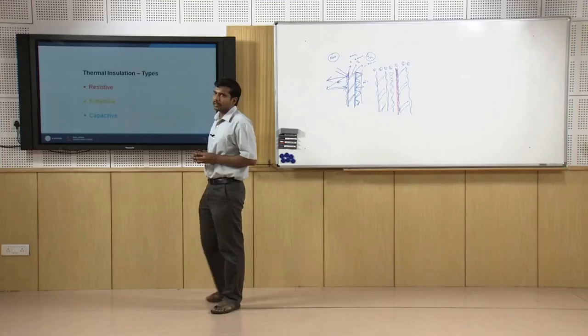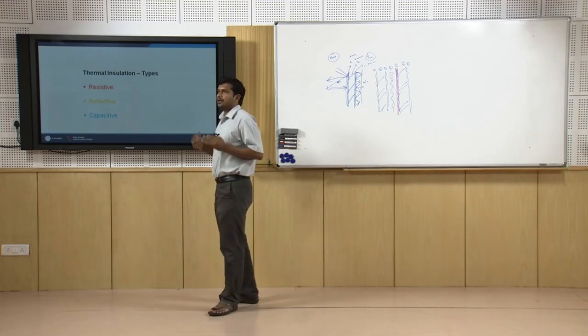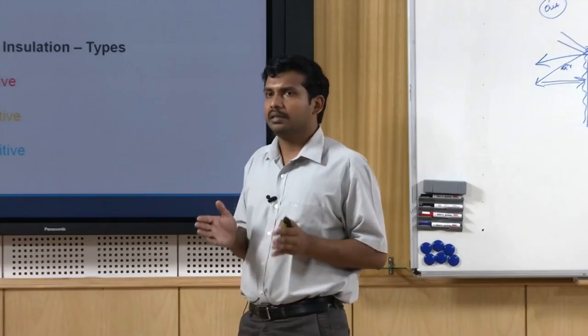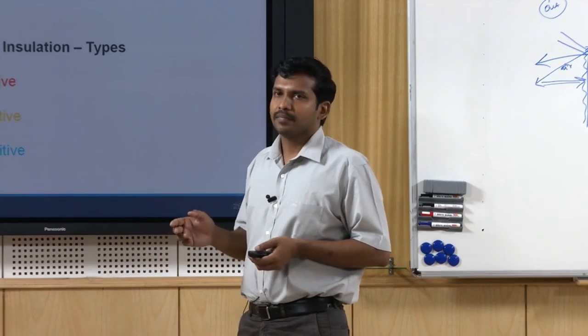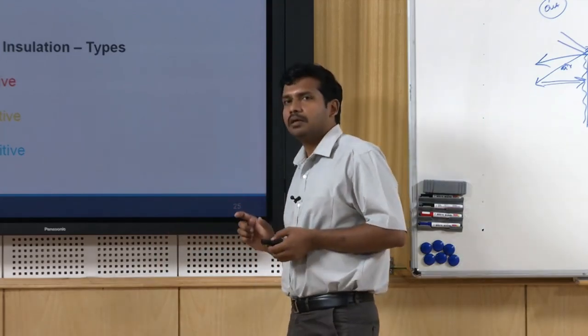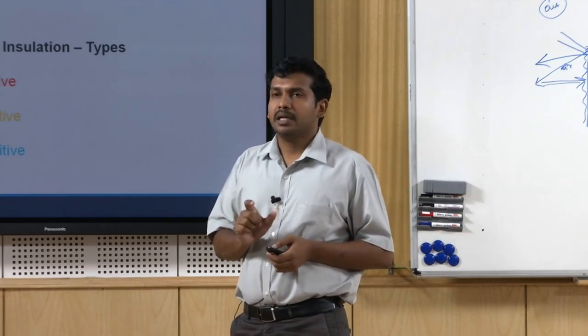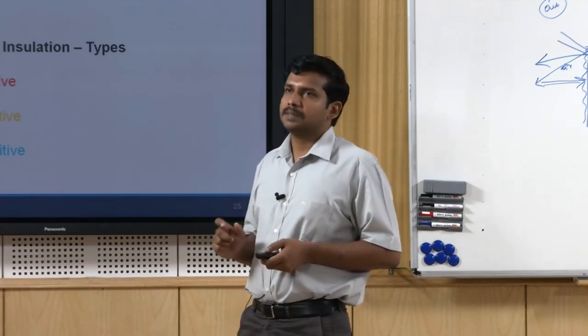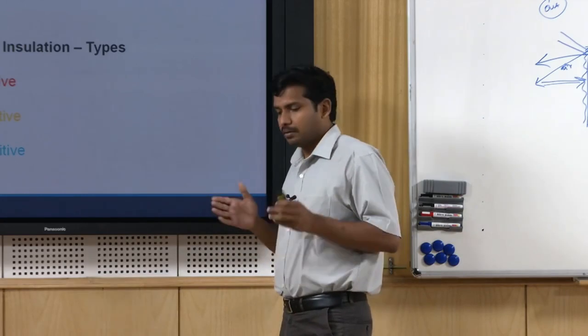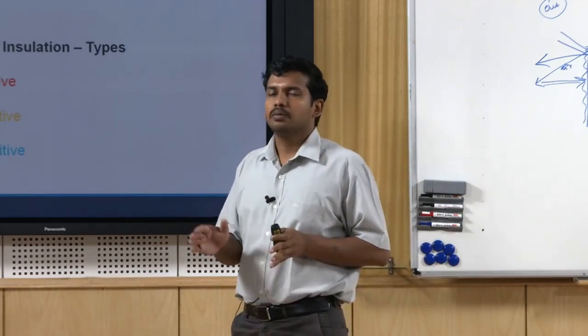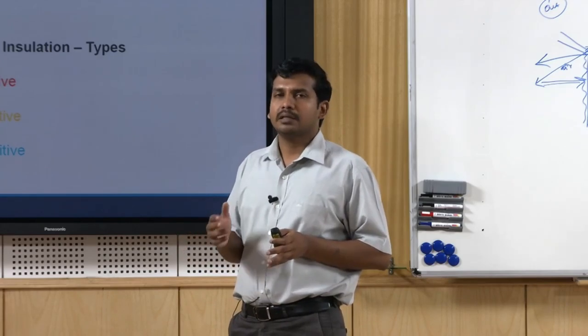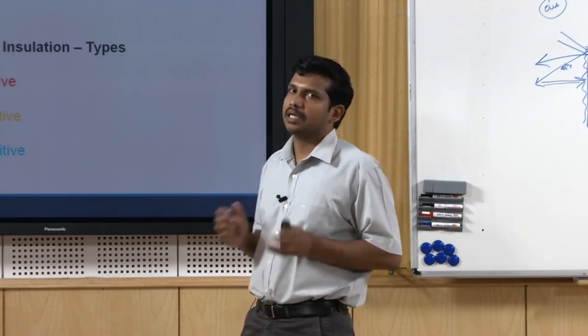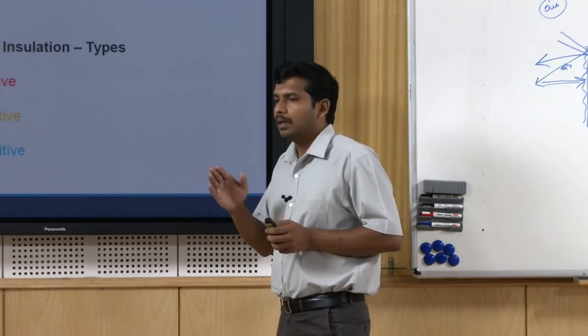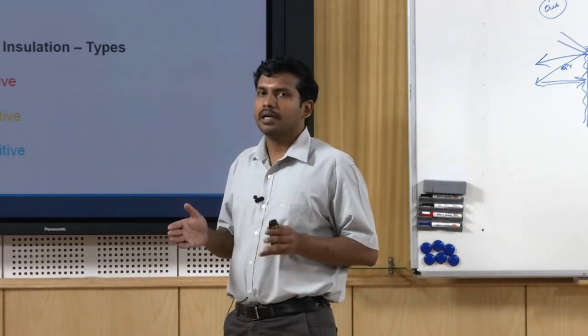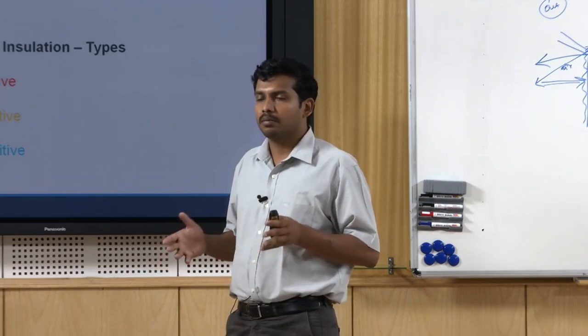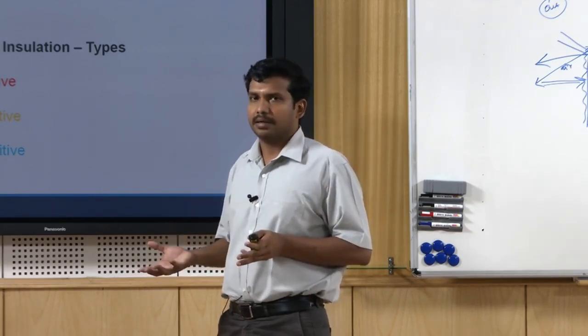But capacitive insulation, say when you use a material like concrete. Typically, people look at concrete as not so useful a material because they think the U value of concrete is high. Imagine a concrete wall of 200 mm or 230 mm thick. Brick 230 mm has a U value of 2.1 watts per meter square Kelvin, whereas a similar thickness 230 mm concrete wall would have a U value of around 3.5 or 3.6 watts per meter square Kelvin. So, naturally, if you do a conductive heat transfer calculation, the concrete wall will give you more heat load or cooling load because it is transmitting a lot of heat inside.